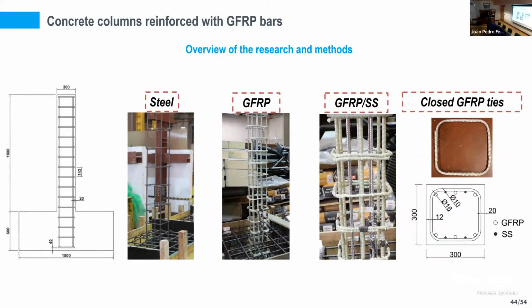And we also assessed the possibility of taking advantage of the combination of longitudinal GFRP bars with stainless steel bars. And the goal here was to assess if we could improve the energy dissipation capacity by exploring the yielding stage of the stainless steel bars, but still maintaining the high durability of the system.